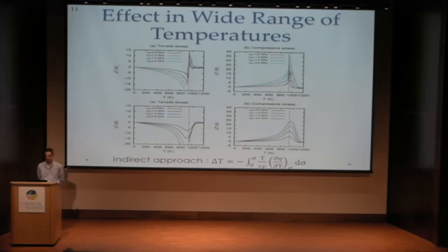So I have a question. In your model, you included just the sigma anti-ferroelectric modes. Is it right? Your effective Hamiltonian, yes. To which extent do these results hold? Because you apply pressure, you have temperature and so on. But we know that with any strain, you can easily shift to, let's say, the sigma or S mode, or to a zone boundary anti-ferroelectric mode, or even to the ferroelectric one. Can you improve your model maybe by including the whole branch of dispersion, these ferro and anti-ferro modes? You just include the sigma mode.